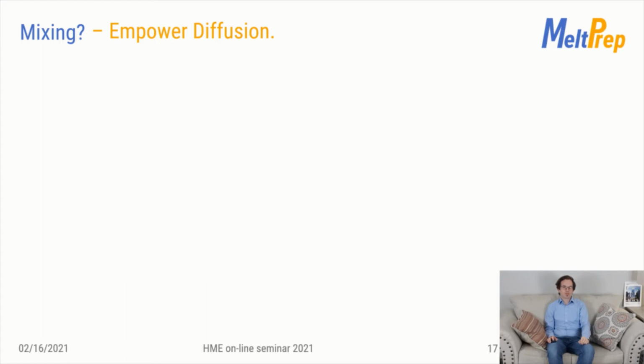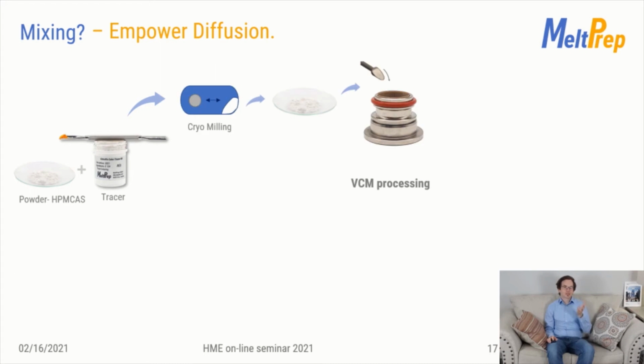The way we usually recommend to do so is milling, preferably cryomilling. Reducing the particle size before processing via VCM will let you obtain an extrusion-like result, an amorphous transparent disc.